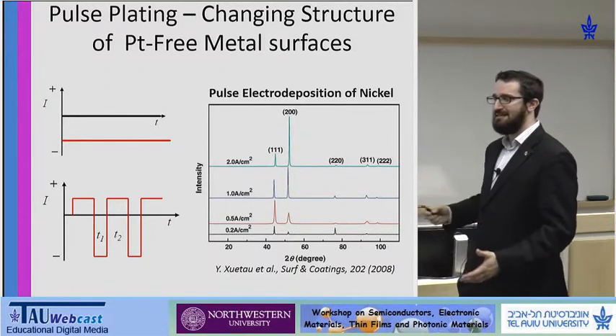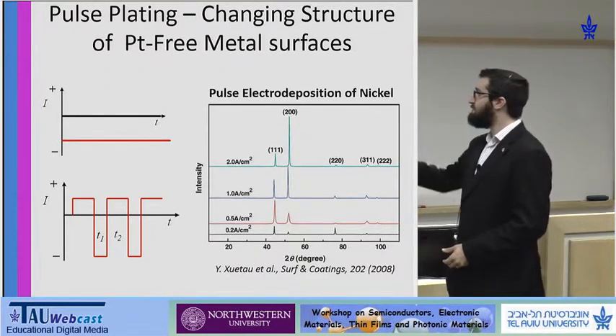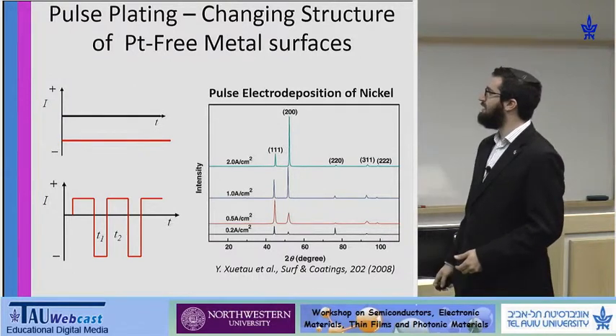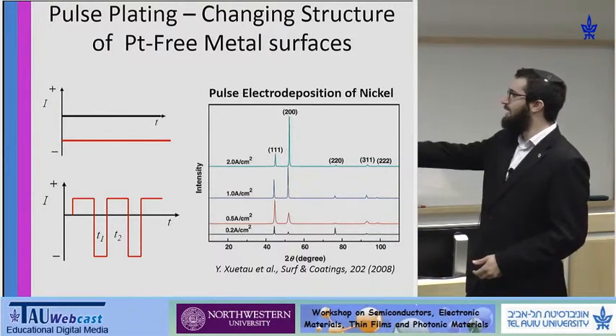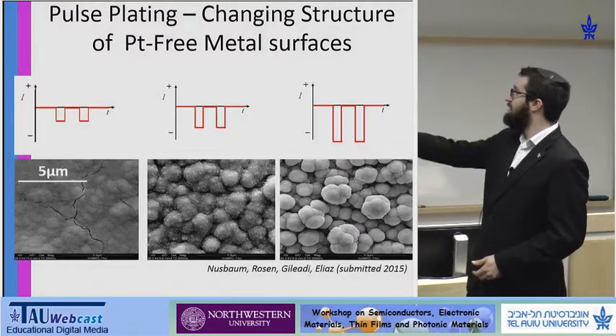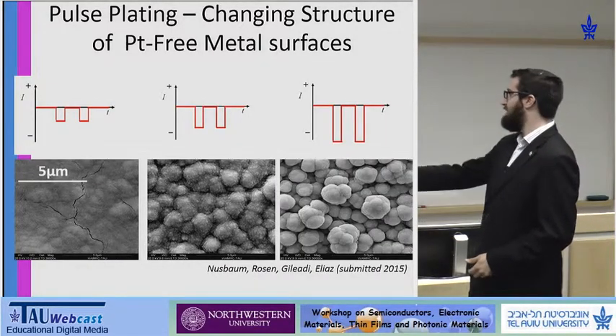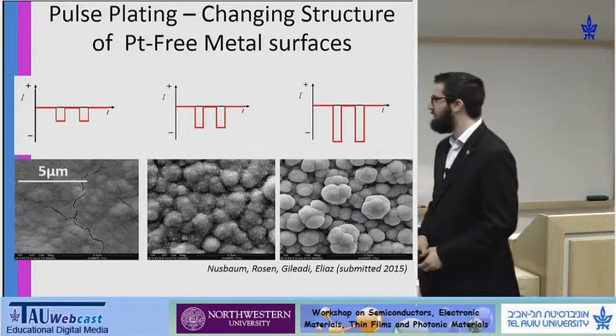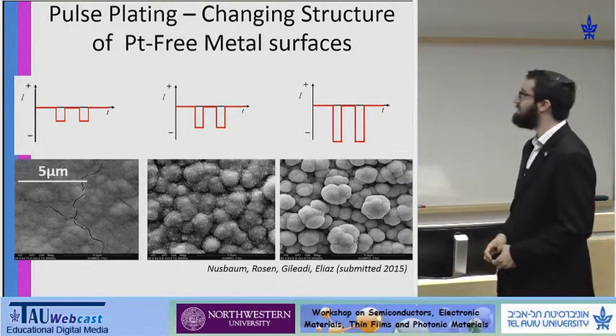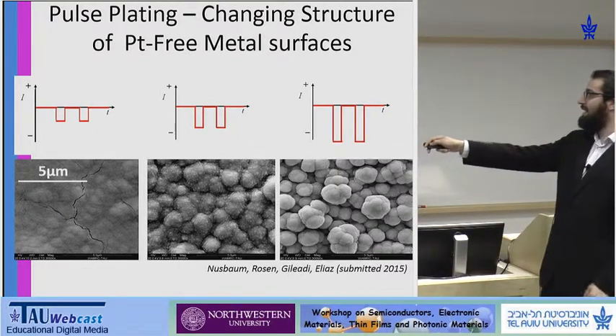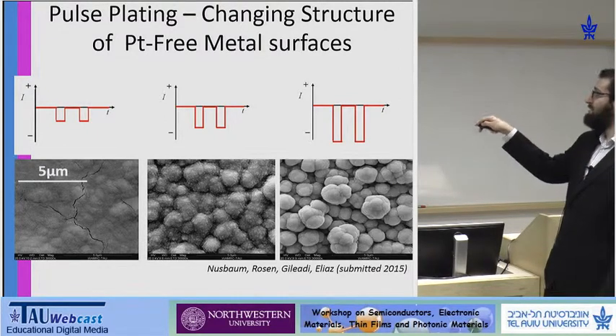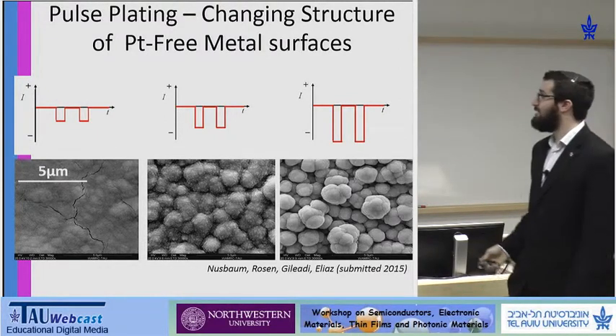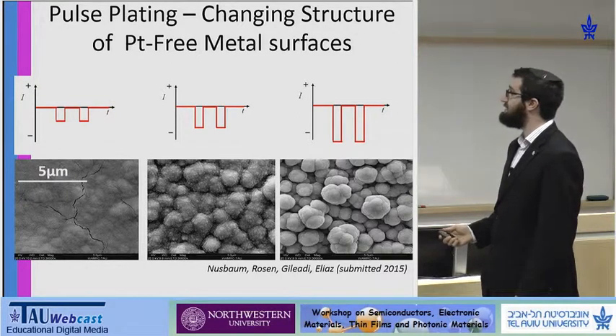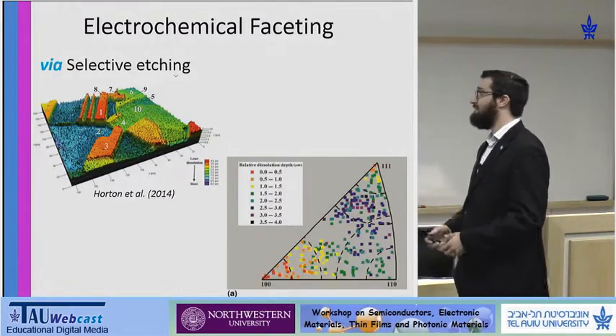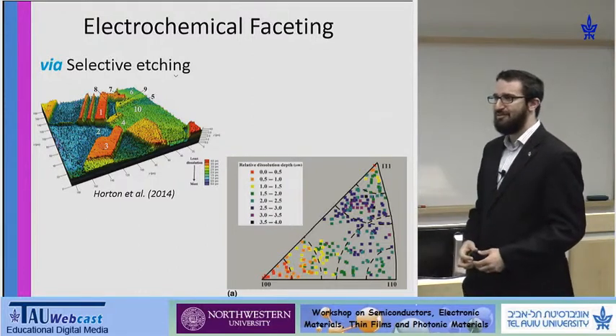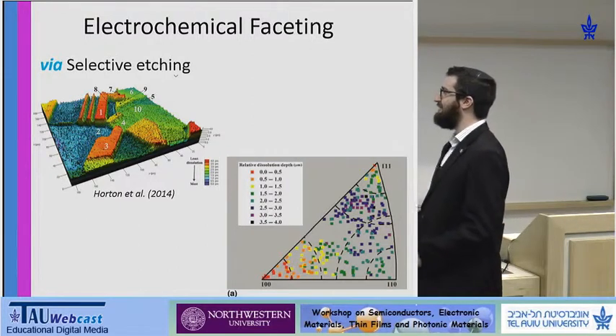And there's a few different mechanisms that are circulating in the literature to explain why you would get a different selective preferred orientation when you apply a pulse of a different strength or of a different frequency, this being an example of something that we have submitted a few weeks ago. We're looking at nickel alloys and how the depth of the pulse affects the microstructure and texture of the resulting deposits. Also, electrochemical faceting via selective etching is also a very nice technique.